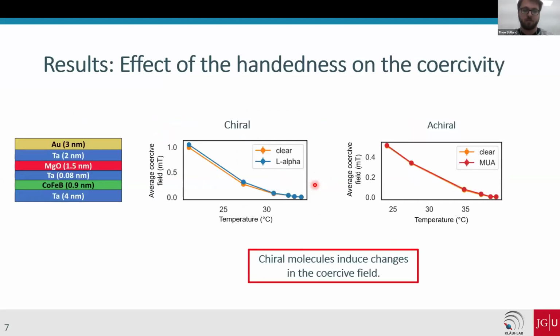So we also measure this out-of-plane magnetization in selective adhesion samples, and we can extract the coercive field. We do this measurement by imaging the clear area and covered area at the same time, so that we have consistent conditions for the measurements.